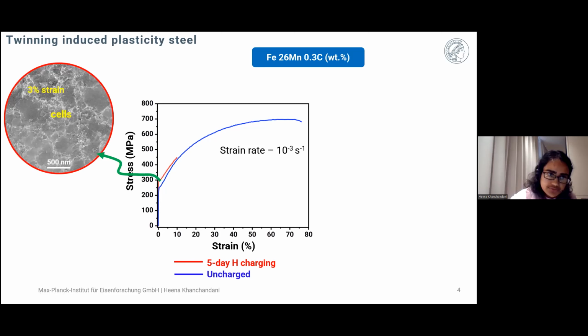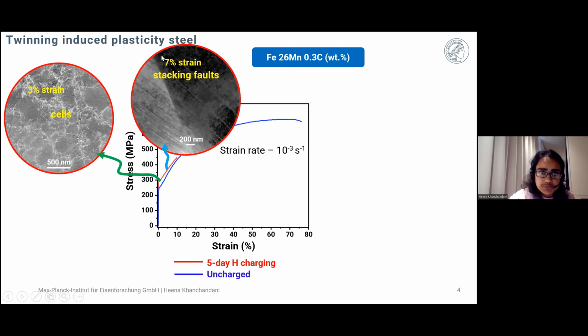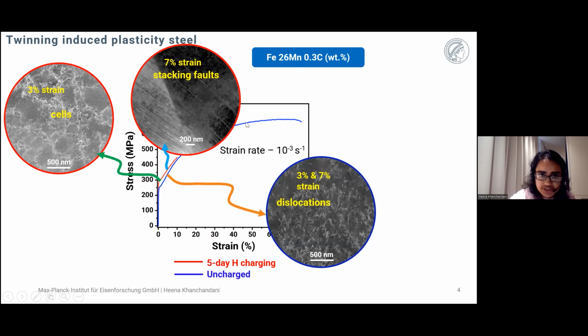To investigate further, we examined the dislocation structure at intermediate levels of tensile strain. We observed that in the hydrogen-charged sample, which was deformed to 3% strain, there was the formation of dislocation cells, while at higher strain, at 7% strain, there was the formation of stacking faults. These features were not observed in the uncharged sample at these deformation levels. There were dislocations observed in the uncharged sample at both of these strain levels, which did not form any features such as dislocation cells or stacking faults. So this shows that hydrogen modifies the deformation mechanism, but how it modifies that is not yet clear, like whether hydrogen is segregated at the grain boundaries or at these dislocation structures.